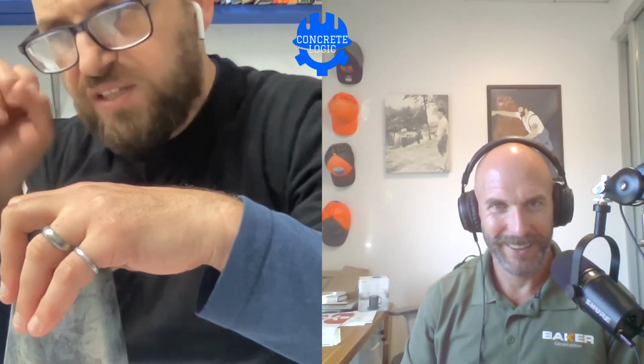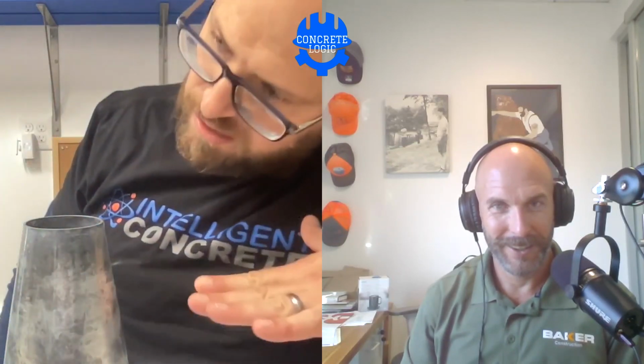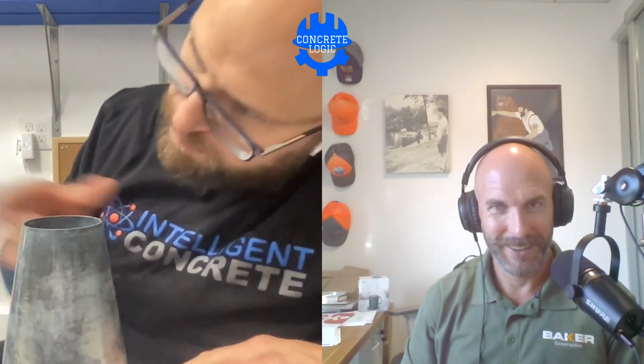There's a test where you take a concrete cylinder. It's not tall enough. And you put a flashlight behind it. And you compare it to other mixes to say how much that concrete has shrunk. And it's specifically for high early strength concrete. And all you're doing is taking a cylinder and pointing a flashlight and measuring the change of the shadow. There are so many amazing tests that are validated and they're at our disposal that can be used.